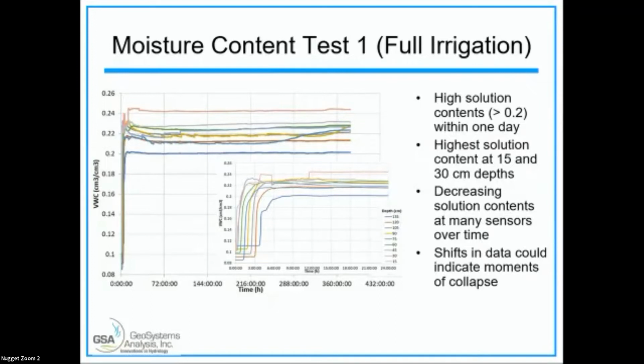And then there was one sensor here around 75 centimeters where it finally started to go back up. But the highest solution content was at 15 and 30 centimeters. And then we also saw these jumps in the data in looking at the short period of time. And we suspect that those are due to actual points in time where things collapsed. Okay, and so we're seeing this big jump in the water content, a big change in the water content.